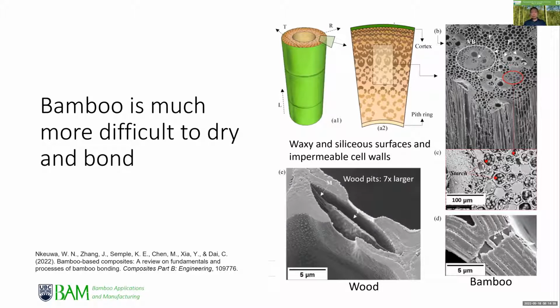One of the attributes of bamboo is that it has a very hard skin, and the skin contains a lot of wax and silica, which makes it very difficult to penetrate when it comes to glue application. Also, if you look at the structure of bamboo, the cross-cellular permeation is very low, because the pit is much smaller in bamboo than in wood. That brings up two major problems: one is the gluing, the other is the drying.